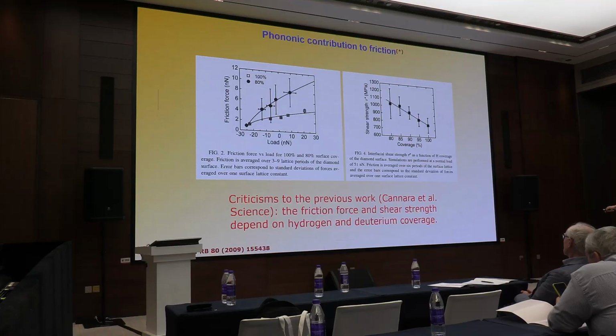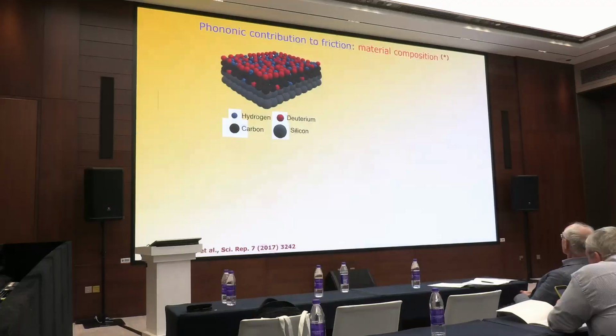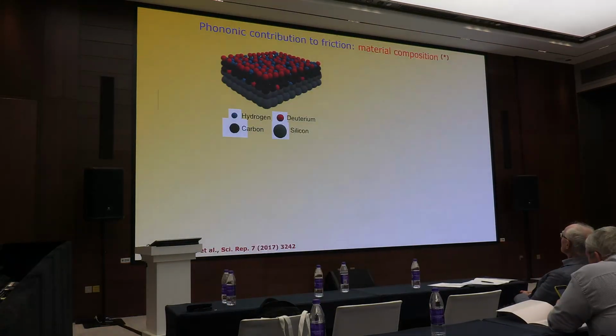The friction force and the shear stress depend on hydrogen and deuterium coverage. They explain that the shear stress depends on coverage. Maybe you don't have 100%, maybe you have 85 and the other sample 50. I don't know. Have you determined the quantity of hydrogen and deuterium at the surface of the sample? Okay, it's a good contradiction. With this contradiction, we started a new study.